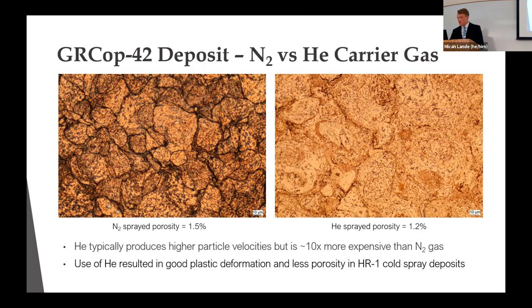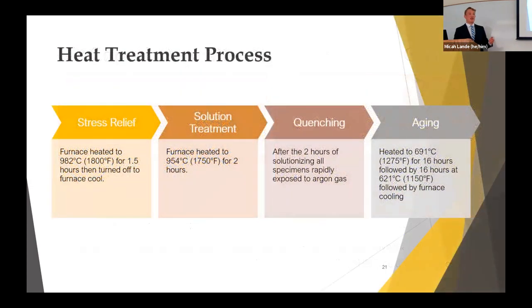So then taking our solids through the heat treatment process. For the beginning of it, we kept some aside to act as our control group in the as deposited state. Then we started with an hour and a half at 982 Celsius for stress relieving. Then after that, it's furnace cooled, meaning we just turn off the furnace and let it cool for as long as it needs to come to ambient temperature.